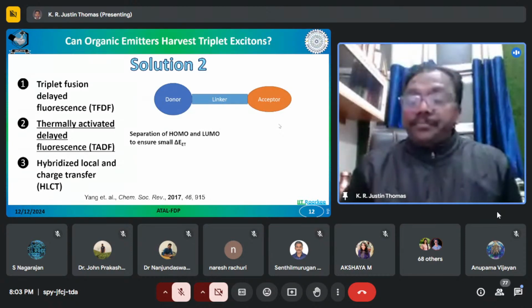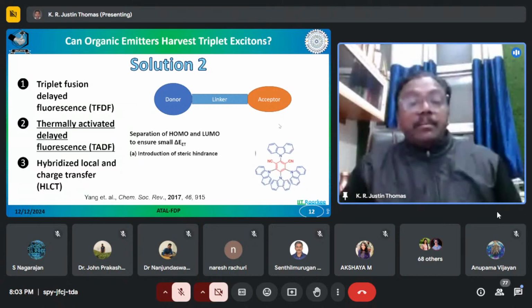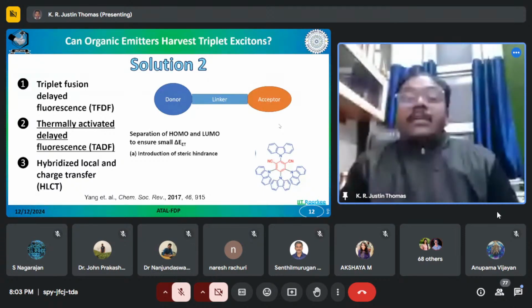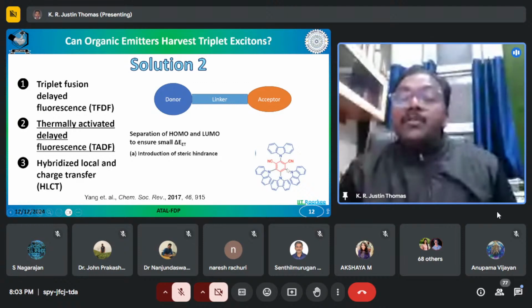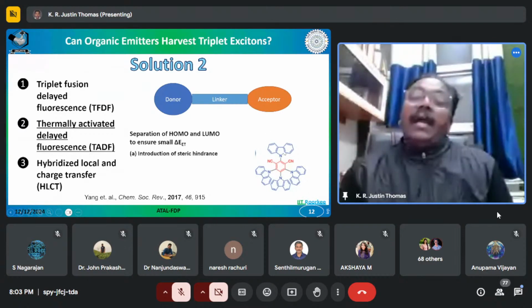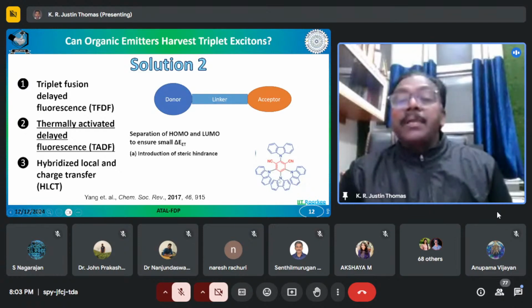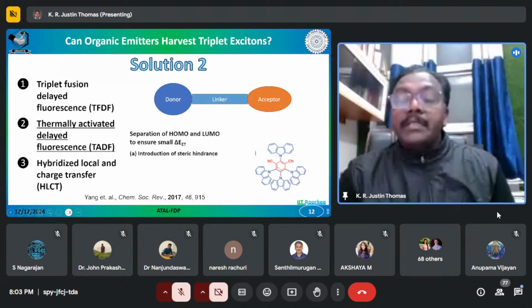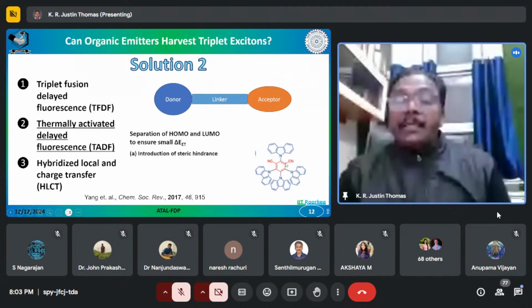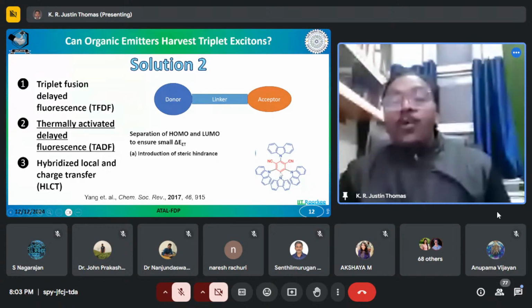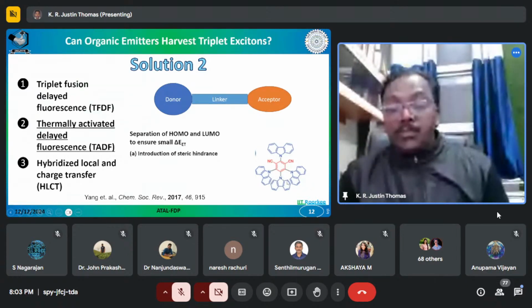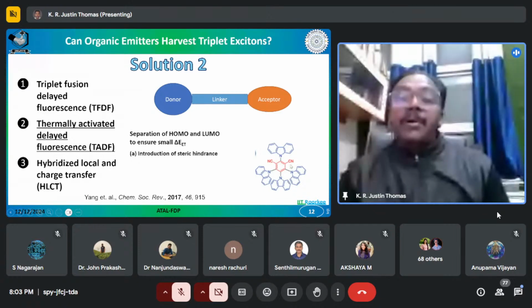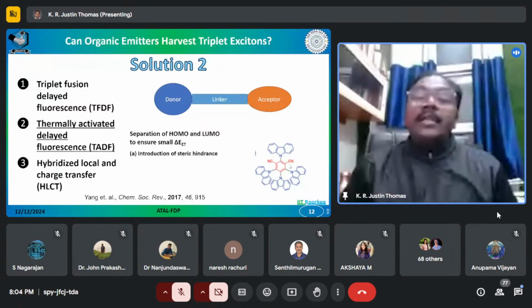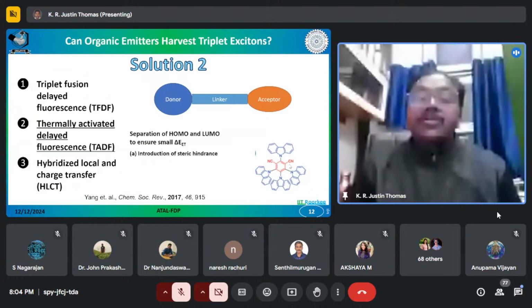Now, if you look at the designs which are prominently reported, they normally have a donor-acceptor structure. In the molecule that I have shown here, there is a cyanobenzene moiety which acts as an acceptor and carbazole which acts as a donor. And in this molecule, there is huge steric hindrance because of multiple chromophores loaded on the benzene. Because of that, tilting takes place. That steric crowding and tilting makes the HOMO confined to the donor carbazole unit, and the LUMO confined to the cyanobenzene moiety. That leads to a small delta EST. That is an important aspect of these molecules.